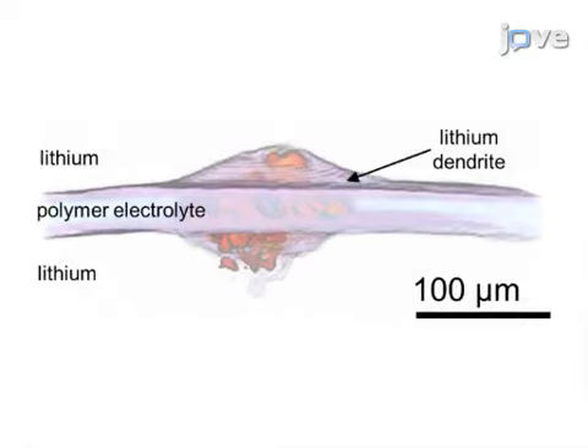Ultimately, X-ray microtomography imaging is used to show morphological changes like dendrite growth in the lithium metal electrodes and polymer electrolyte as a function of cycling. The main advantage of this technique over existing methods like electron microscopy is that the resulting images show the interior of the electrode and electrolyte layers, revealing structures that are hidden using traditional imaging techniques.